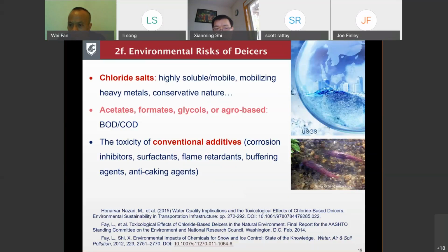Additives are certainly one way out, because in the short term, at least, I don't see people getting rid of the chloride salts altogether because they're relatively affordable. I mentioned the acetates were 20 times more expensive, roughly speaking. So yes, we still have to use chlorides. So most agencies are doing salt reduction programs, trying to minimize the amount of salt without compromising safety and mobility. So there's some room for improvement in those regards, both in the management domain and in the technology domain.